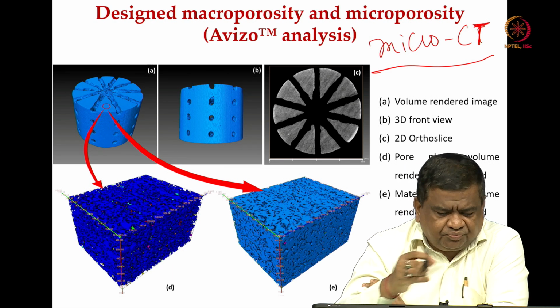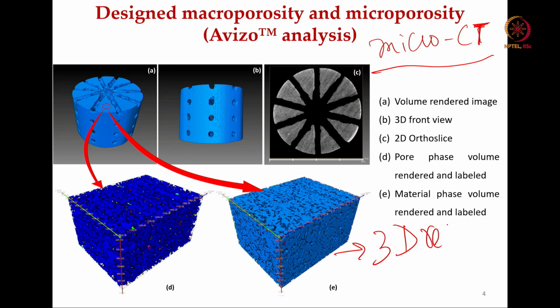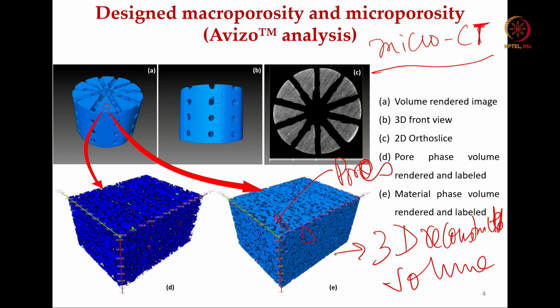So, what you see here is essentially a 3D reconstructed volume, and in this 3D reconstructed volume you can clearly see these are like pores. This is taken from your region of interest or volume of interest, and when you put this volume of interest in x, y, z directions, you get this kind of porous structure. And we are more interested in the gradient in porosity, to see that by introducing the gradient in porosity, you can develop better properties, or properties are being optimized or compromised. We have used a specific software platform, Avizo software, which is used for quantitative analysis of the 3D microstructure.